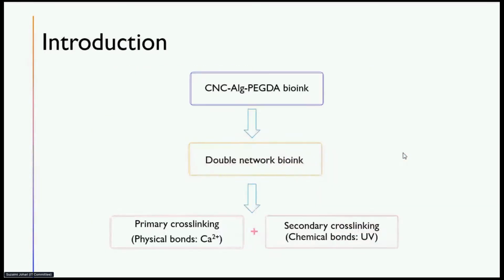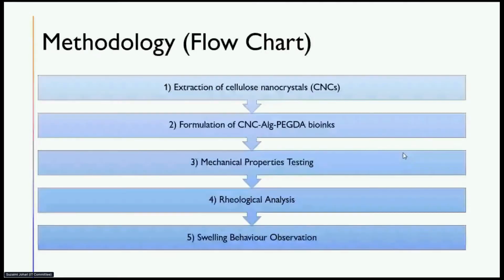Next slide. So from these 3 biomaterials, which is a mixture of both natural and synthetic polymers, we introduced a double network system, which will help to improve the mechanical properties of the hydrogel. So this double network bioink is formed from 2 cross-linking mechanisms. Number 1 is the physical bonds by calcium ion interaction, and the secondary cross-linking by UV. So in this study, we attempt to formulate a bioink that will satisfy the properties of the cartilage. Next slide.